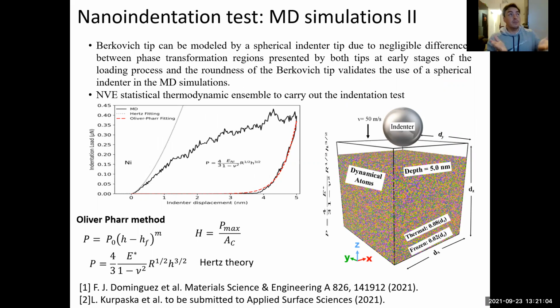So now, as I said before, the Berkovich tip can be modeled by a spherical tip because of the roundness of the tip, and also the negligible difference between the phase transformation regions presented by both tips at this early stage. We also performed some MD simulations for the Berkovich, and I don't see any difference. So to me, it's easier to do it with a spherical indenter tip.